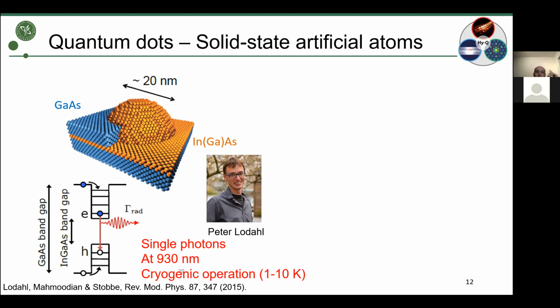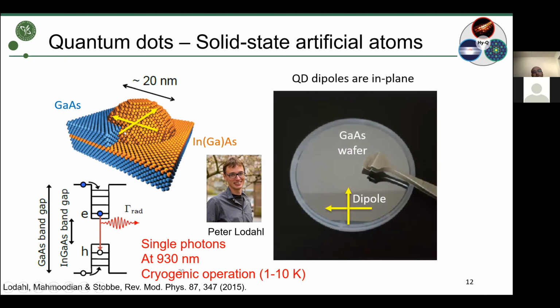Now, another interesting thing about quantum dots is that the transition dipoles that represent how the dot emits light are very well known and can be determined in advance. They're basically two, orthogonal to each other, and they're in the plane. And that's a very important fact because it allows me to engineer my photonic nanostructure, as you will see in a while, knowing very well in advance how the dipoles are oriented. And so if you look at the typical gallium arsenide wafer, that's where we have a lot of these quantum dots. You cannot see them because they're extremely small. But we know how these dipoles are oriented once we find a quantum dot. So we know how to align our nanostructures to it.